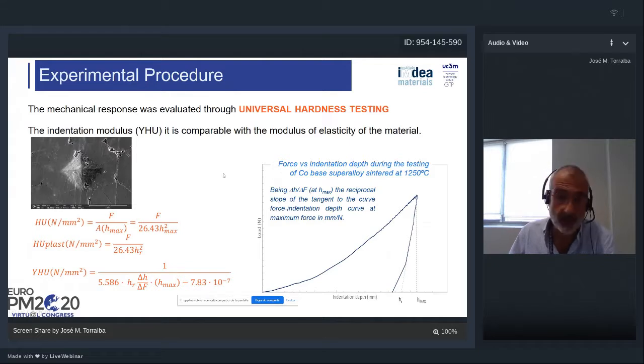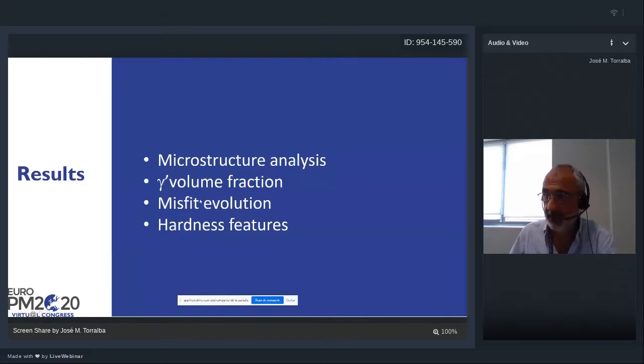This is quite a localized mechanical property, so maybe it's just to give us an idea of the general mechanical properties, but we have to perform also hot compression tests at high temperature in order to see how the misfit really affects this property at high temperature. Anyway, we have developed the microstructural analysis, the gamma prime volume fraction measurements, the misfit evolution, and also some hardness features.